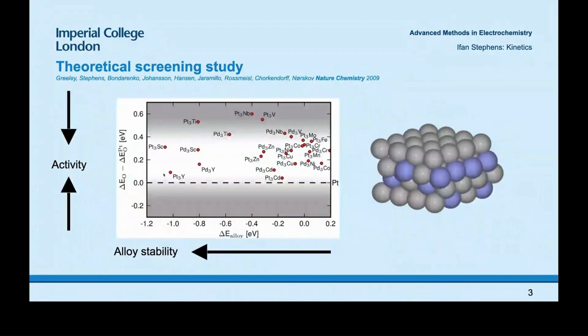So the first catalyst we actually tested was palladium yttrium. Initially, we measured the oxygen reduction reaction on it, and it looked like it was pretty active, and we also tested platinum, and it looked like the palladium yttrium was actually more active than platinum. So this was really exciting because palladium is usually less active than platinum, but if we could get palladium to be more active, that would be really good. And we got really excited, and all the theorists got excited and said this proved that the theory was correct.